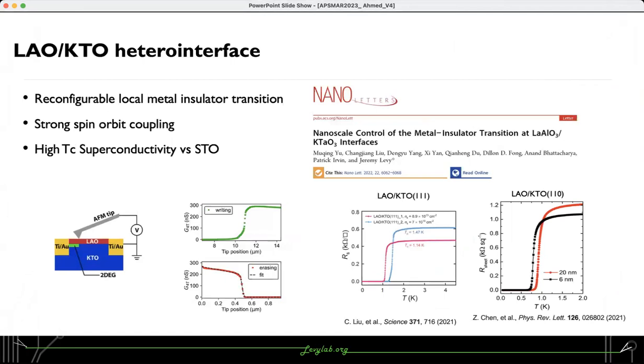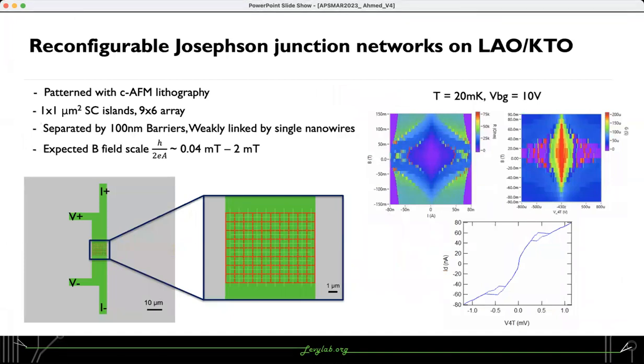A similar complex oxide heterostructure system that acquired lots of attention recently is the interface between LAO and KTO. It exhibits a similar metal-insulator transition to LAO-STO. However, it shows a stronger spin-orbit coupling and nearly 1 order of magnitude higher superconducting Tc, which might make it a more desirable candidate for certain applications. Based on that, we have recently started to investigate a very similar approach to the same problem. Here we create arrays of weakly coupled superconducting islands by directly patterning the device with CAFM lithography.